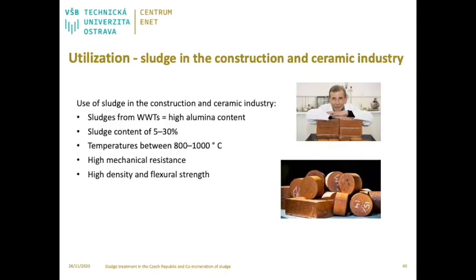A number of researches are currently underway that focus on the use of sludge as a substitute for ceramic clay and clay for brick production. Sludges from the wastewater treatment, which are characterized by a high alumina content, are widely used for this purpose. Materials with a sludge content of 5 to 30%, from which bricks are fired at temperatures between 800 to 1000 degrees Celsius, are tested. Products show high mechanical resistance without deformations and defects. They have high density and flexural strength.